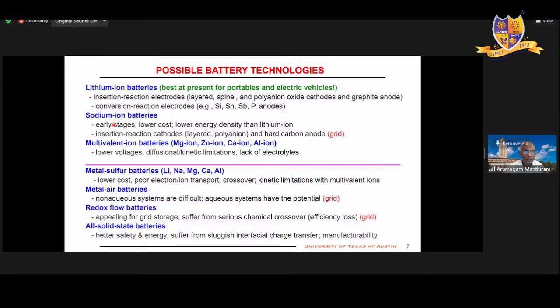But sulfur is an insulator, electronic insulator, poor lithium ion conductor. Remember, I mentioned here, the electrodes should have good electronic conductivity, good ionic conductivity. That is pretty bad, unfortunately, with the sulfur because it's an insulator. And also sulfur dissolves, goes from one electrode to another electrode. It's a problem, messing around. But sulfur stores 10 times more charge than the other cathodes. So you can store a lot of energy, but unfortunately it has the other problems.